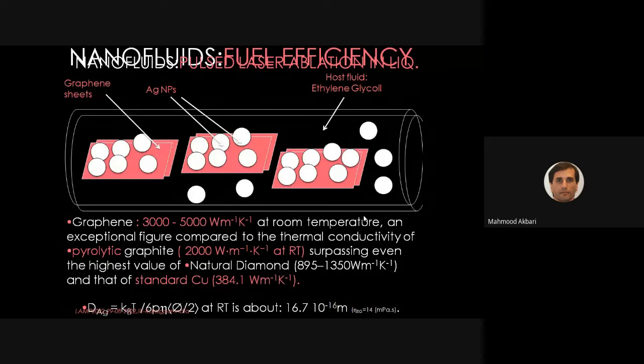First of all, ablating graphene in ethylene glycol, making nanoplatelets and nanosheets of graphene in ethylene glycol, then immersing the silver target in it and irradiating to ablate silver nanoparticles, which, because silver is polar, would definitely come and graft, at least by van der Waals forces, on the surface. Maybe not a chemical adsorption, but at least a physical adsorption. Next, please, Prof.